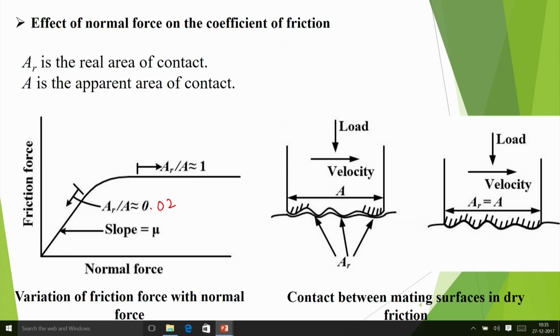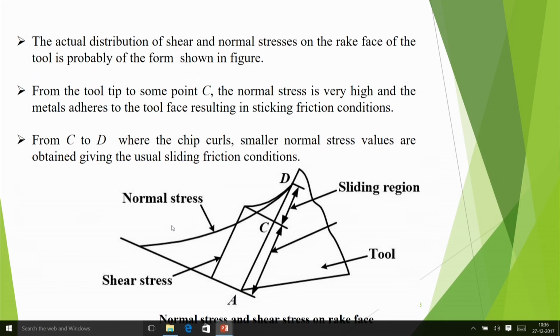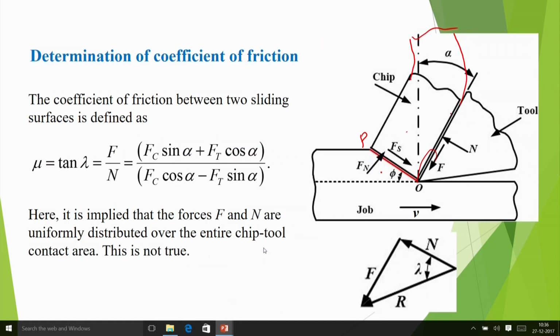An asperity based model of friction is usually taken, and then people do a lot of studies. These asperities are deforming in an elastic manner, also they are deforming in a plastic manner. So, elastoplastic deformation, the effect of various things and chemical aspects, all these have to be considered in detail, but phenomenologically we are observing this type of behavior that I have shown here. So, friction force actually is very small and follows Coulomb's law if the normal force is less, and if the normal force is high, then it becomes the constant friction condition. So, that is why you are getting this type of distribution, but right now I have done Merchant's